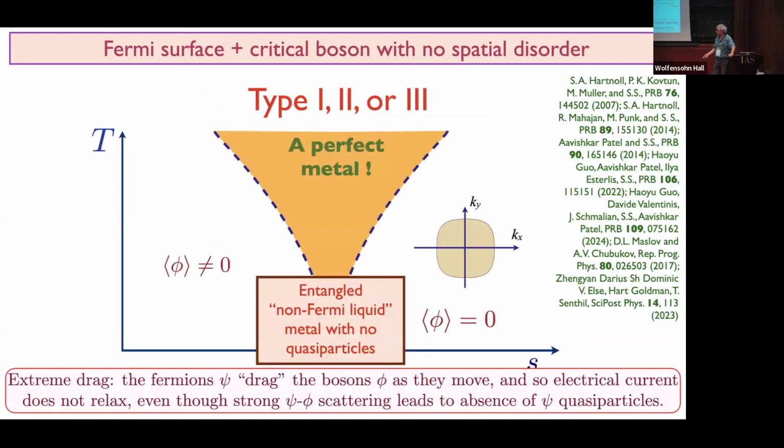Another interpretation is what's called drag. This issue also comes up in what's called the electron-phonon problem, which was first looked at by Bloch in the 1930s in a paper written in German. He derived what we now call Bloch's law, which is that the resistivity of a three-dimensional metal at low temperatures due to electron-phonon scattering vanishes as T to the power 5. He just computed the probability that an electron will scatter off a phonon and put that into Boltzmann's equation.